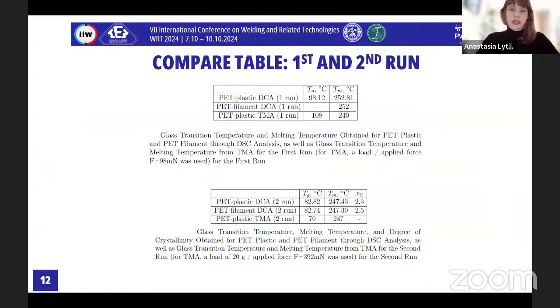The glass transition temperature obtained from the DSC method for both filaments of PET can be considered equivalent, whereas the glass transition determined by the TMA method is lower. This discrepancy may be attributed to differences in experimental methodologies, as during the first run in DSC, the material reaches melting temperature before cooling, but when we use TMA, as I mentioned, I'm heating it to a temperature of 210 degrees. It's impossible to heat it to melting temperature because it can deform the sample and we'll just fail our experiment.